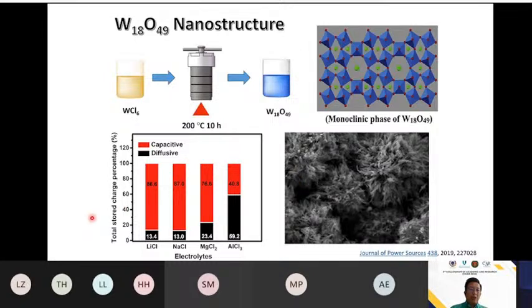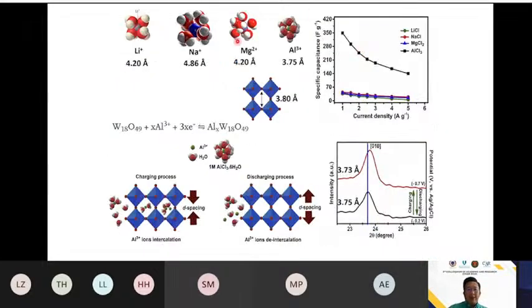Then we study the charge storage under different electrolytes. It is proven that under the aluminum chloride electrolyte, we are able to store a very high charge, whereby most of the charge is in the diffusive nature. What does it mean? It means that right now, the aluminum ion can actually diffuse within the structure of this tungsten oxide. Then we study the crystal void and find that it is really nice, because the crystal void is 3.8 angstrom, which is just nice to fit the 3.75 angstrom of this aluminum ion.